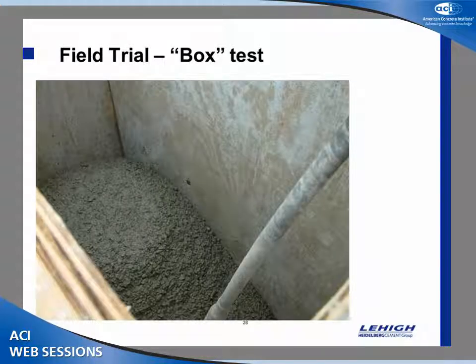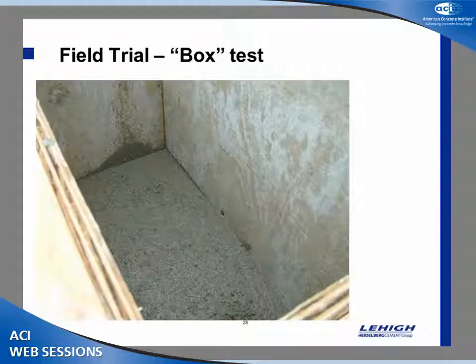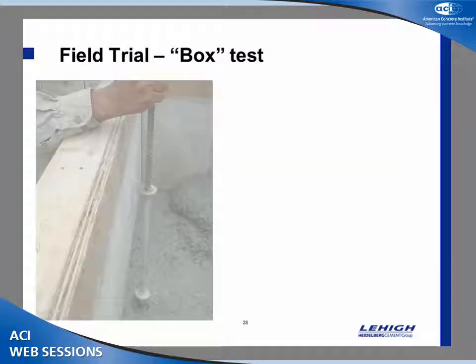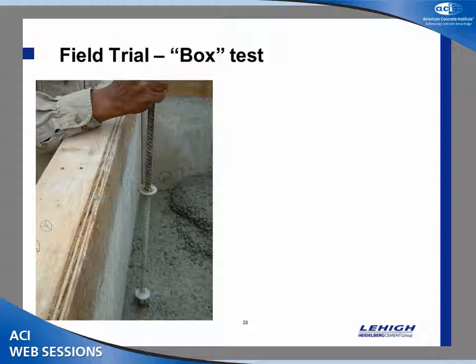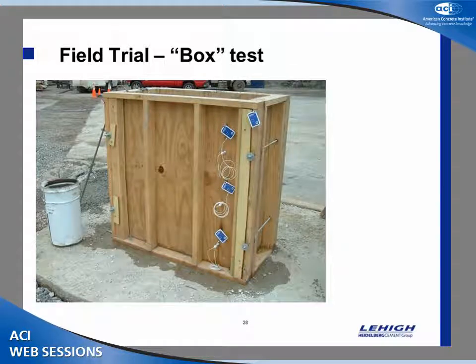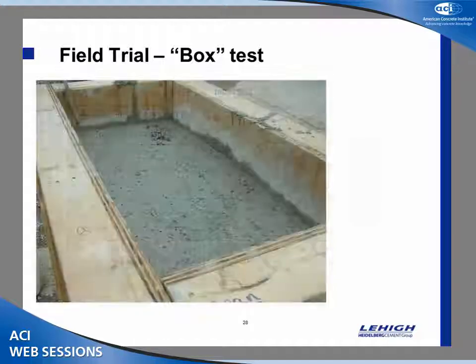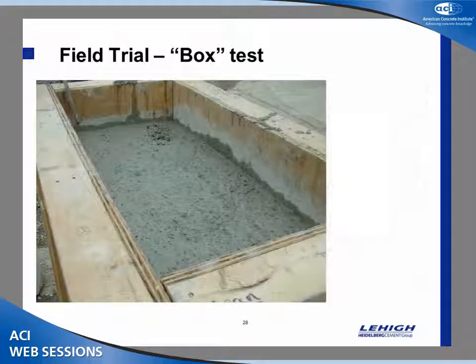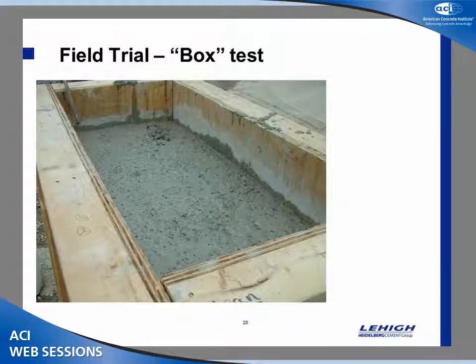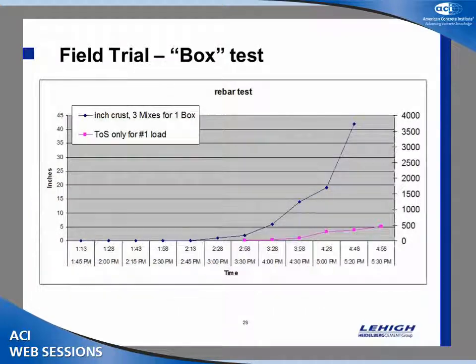So you put the concrete in, and you vibrate it, and then you wait. And you stick it in, right? And they take a measurement from here down, and you record that measurement. Of course, we had to look like we knew what we were doing, so we stuck on some thermocouples there. So again, you fill this up and you keep poking. And so you end up with a graph. It's this curve that you're looking for. You're looking for a certain slope there. So you want to see a certain stiffening.